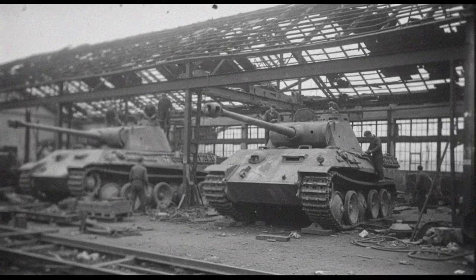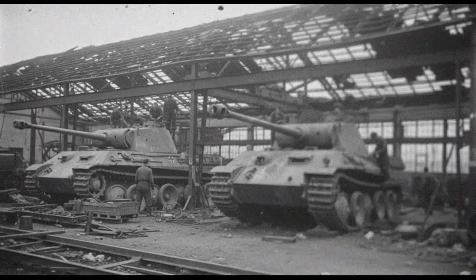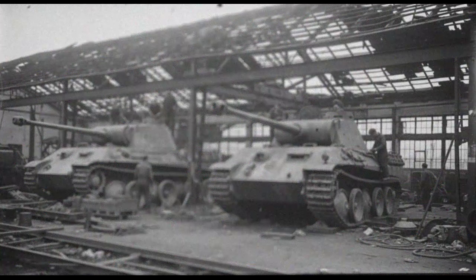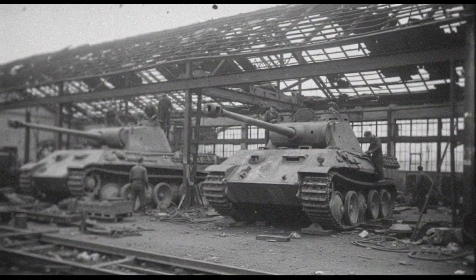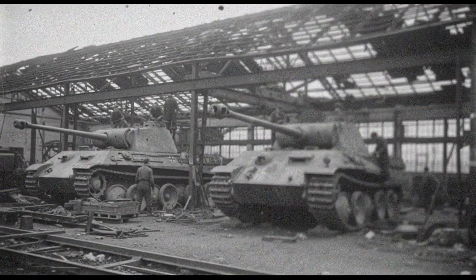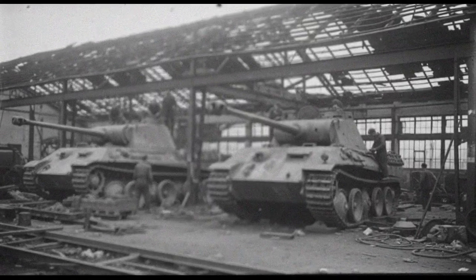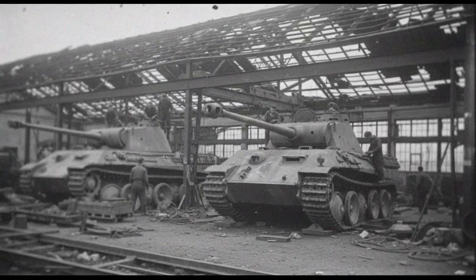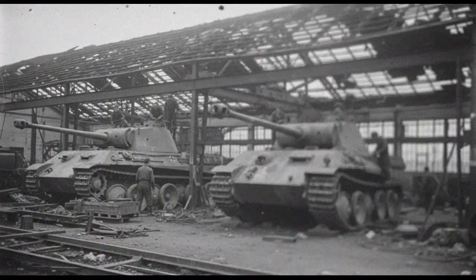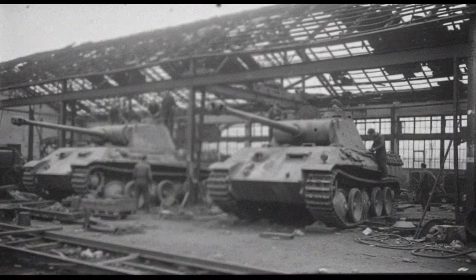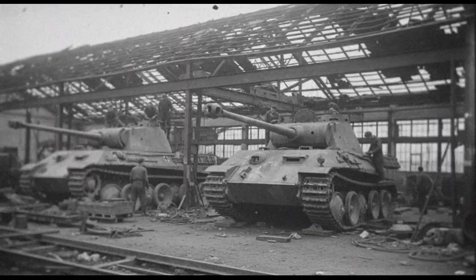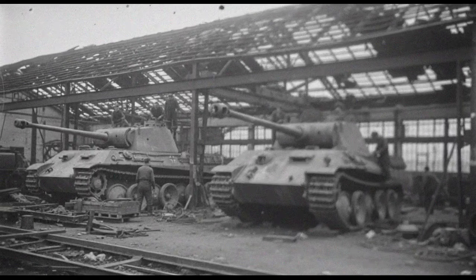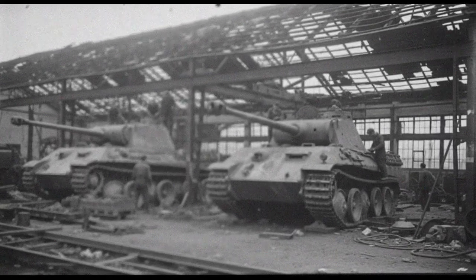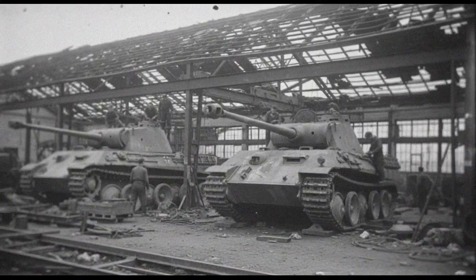Molybdenum, which improved the steel's response to heat treatment and increased toughness, was similarly reduced or replaced with less effective substitutes. To compensate for the inferior alloy composition, German metallurgists adjusted their heat treatment processes. They tried different quenching methods, varied the tempering temperatures, experimented with alternative hardening techniques. Some of these adjustments helped, some did not.